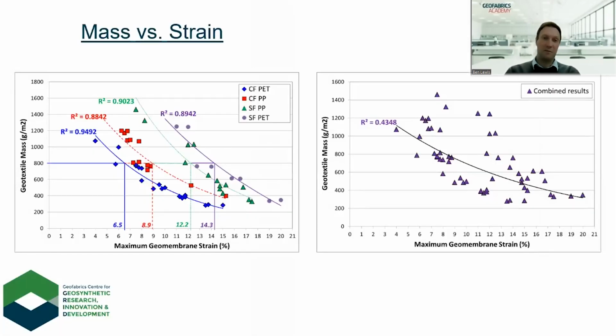And we tested about 40 different materials from all over the world and categorized them into continuous filament polyester, polyprop as well, and staple fiber polyprop and staple fiber polyester. And what it essentially told us was that continuous filament polyester for an 800 gram mass induced a strain over a certain HDPE of 6.5%. And we compared that to a staple fiber polyester geotextile for the same mass, only induced a strain of 14.3%. So it really just highlighted that you can't just look at mass for performance of cushion protection.